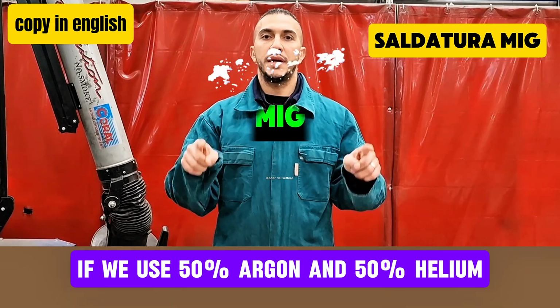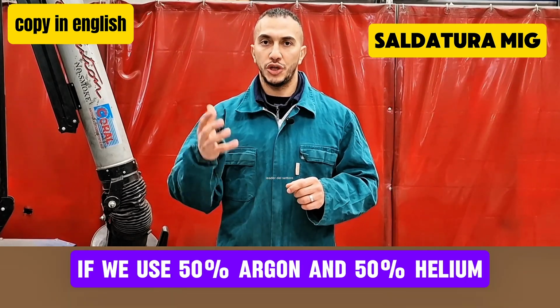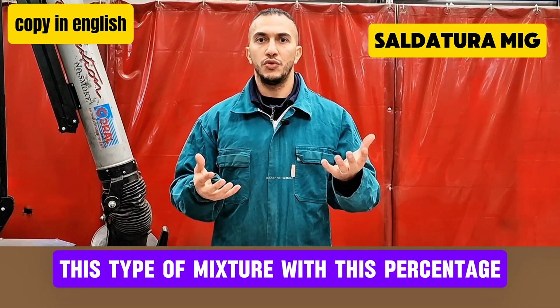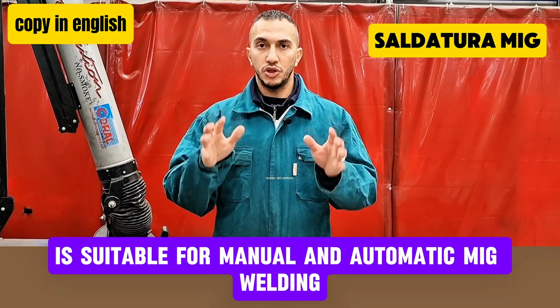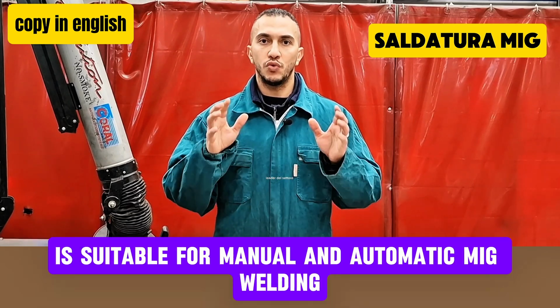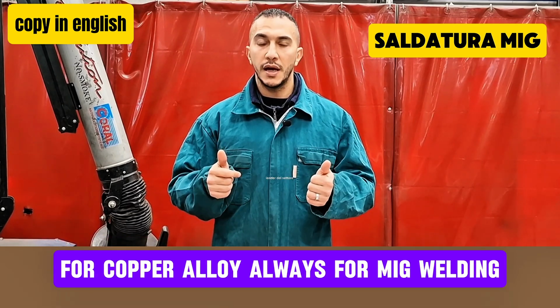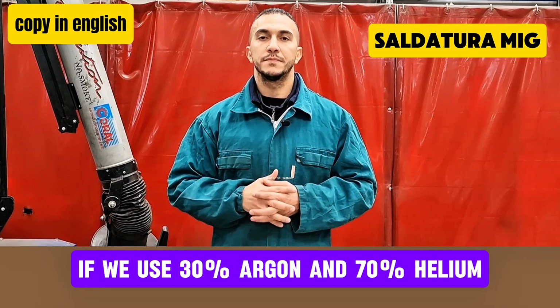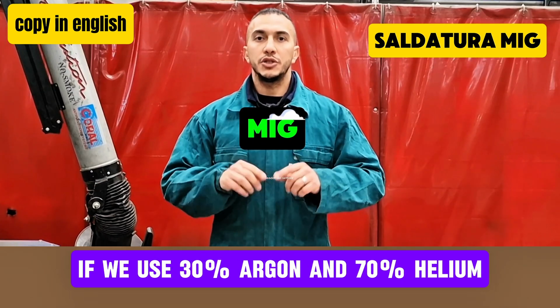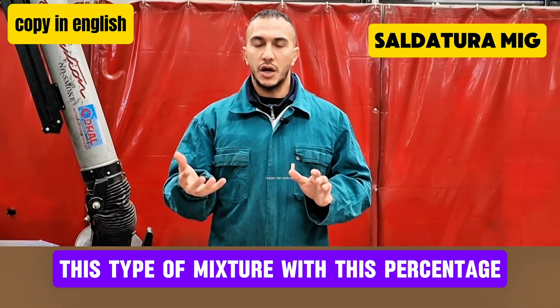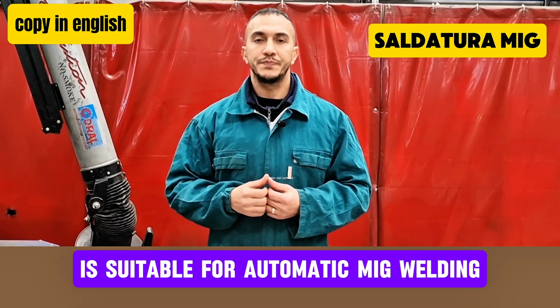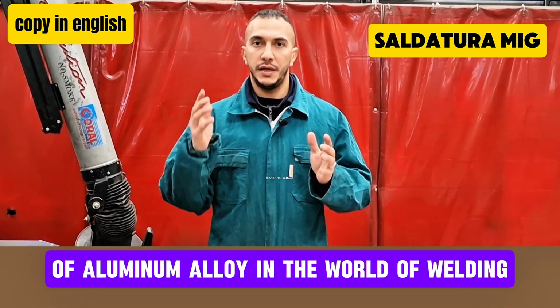Always for MIG welding, if we use 50% argon and 50% helium, this type of mixture is suitable for manual and automatic MIG welding of copper alloy. Always for MIG welding, if we use 30% argon and 70% helium, this type of mixture is suitable for automatic MIG welding of aluminum alloy.